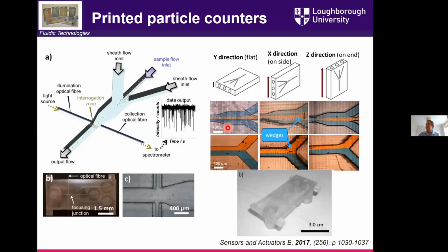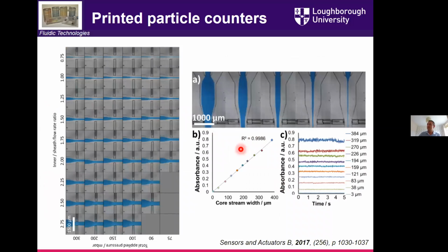All of our printed devices in SLA, because we wanted to have small channels, needed to be printed on the surface. And so the small grooves that you can see here are actually all on the surface of this device. Okay, and that's because we can then get much narrower channels. We can get the unset resin out of those channels much easier than embedding a flow channel deep within an SLA material. So we've got channels on the surface, which we then seal over with a piece of tape. We can put a fiber optic in there. We can then integrate these into our droplet reactors. And you can really control the size of that jet in a very simple, easy to make device.